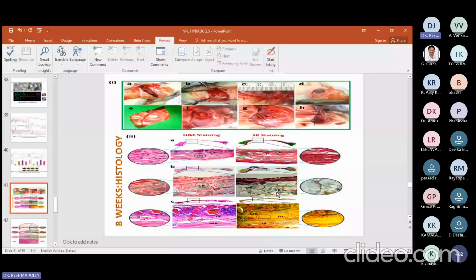But the drawback with the Cerabone is that it is still present at the defect site. So it means it will take more than 8 weeks to get degraded out of the body. So this was the major accomplishment, achievement we can see in case of our study.